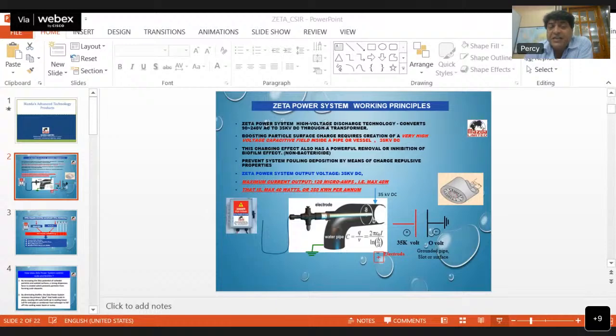So this Zeta increases the Zeta potential. It increases the colloidal repulsive force. There is a dispersion force, and because of that, the particles that form scale or the biological film always remain in suspension. They don't stick. So by increasing the Zeta potential of colloidal particles and wetted surfaces, a strong dispersion force is created, which prevents particles from forming scale deposits. And scale is a very major issue in the industry.